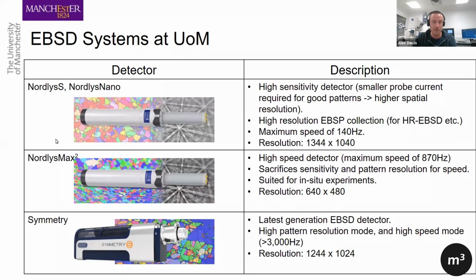And then we've got a slightly modified version of the Nordlys, which is the NordlysMax2. Now, this is a high-speed detector, so it sacrifices sensitivity, so we can collect patterns much more quickly. And this is quite well suited for in situ experiments. For example, Jack and I have run some experiments on our Nova system, which is equipped with this camera, using an in situ heating stage, so we can collect patterns quickly as we're increasing and dropping in temperature. And you'll see that the resolution of this camera is much lower, and that's to get that speed much higher.